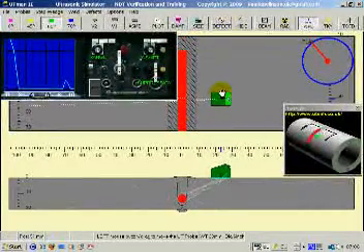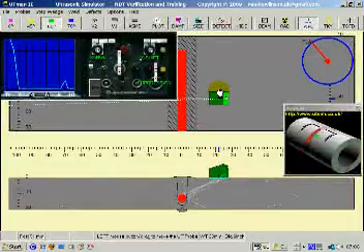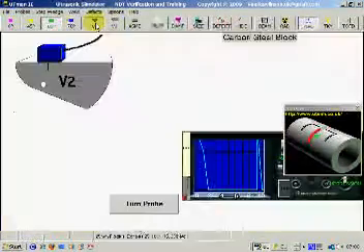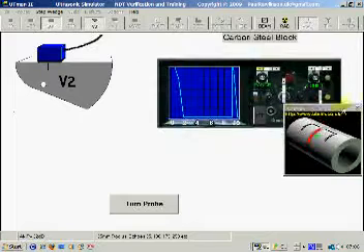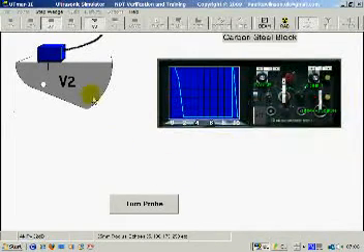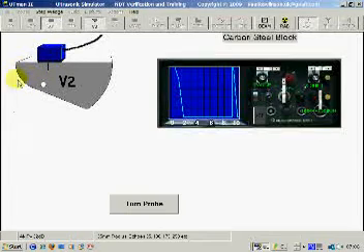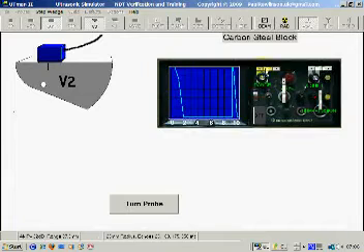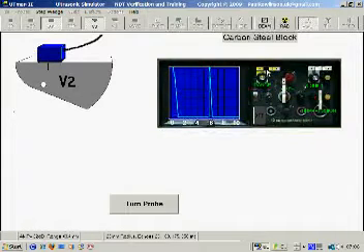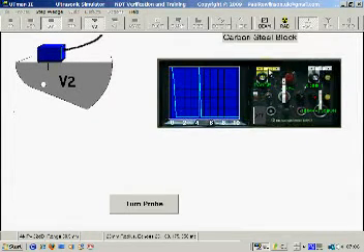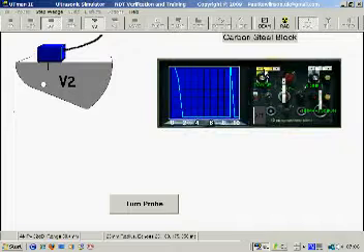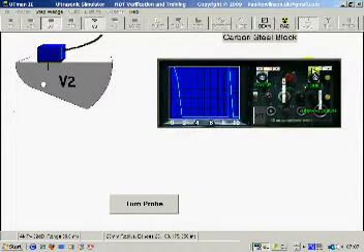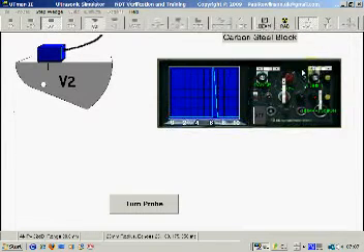Before we can test this weld and detect this defect, we have to calibrate. To remind you, to calibrate the angle probe, this is a 60 on the V2, 25mm radius and 50mm radius. We're looking for two echoes. Set one at 25 and the other at 100.